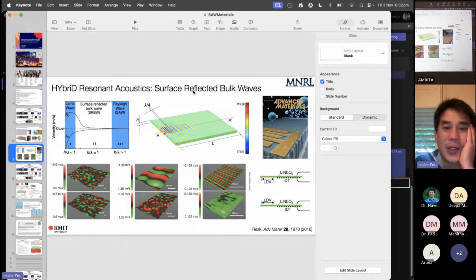All right. We call it surface reflected bulk waves because if I call it Lamb waves, people stone me for heresy. But if you look at this, this is what it is. If you look at a pure surface acoustic wave, it is on top, on the same surface as the electrodes, those finger-like electrodes. You see the surface wave, like an earthquake, right? And if you flip to the bottom, you see almost no energy. So everything's localized on this surface. If you look at the hybrid wave, it's still in some ways a surface wave on one side, but because it leaks its energy, it's like a bulk wave throughout the thickness. So it's still confined on the surface, right?